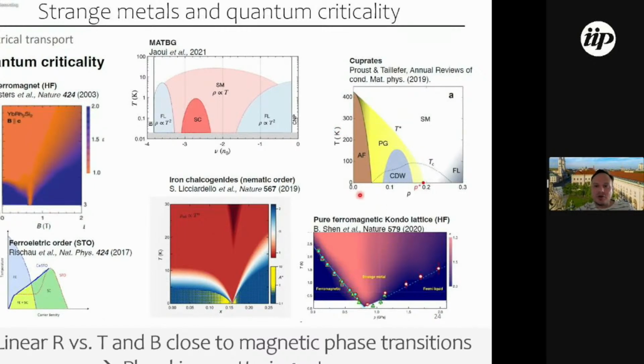And accompanying these phases, there are strange metals. And these strange metals are usually living in completely different density or phase space regions than, for example, normal or Fermi liquids. These strange metals are identified phenomenologically by linear temperature dependencies and magnetic field dependencies at ultra low temperatures. So unlike a Fermi liquid, which usually scales as a power law as a function of temperature, these strange metals scale linearly with T.